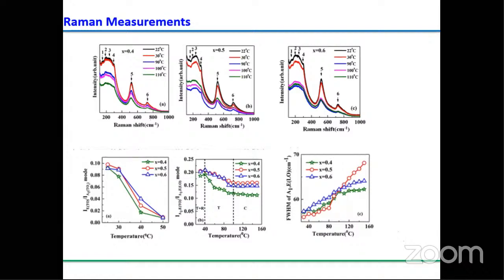So from Raman measurements, what we observed is that our materials have the morphotropic phase boundary at room temperature, and it possesses two kinds of phase transitions. One phase transition is rhombohedral to tetragonal at 40 degrees centigrade, and tetragonal to cubic or pseudo cubic at 100 degrees centigrade. This is what we observed in Raman measurements.